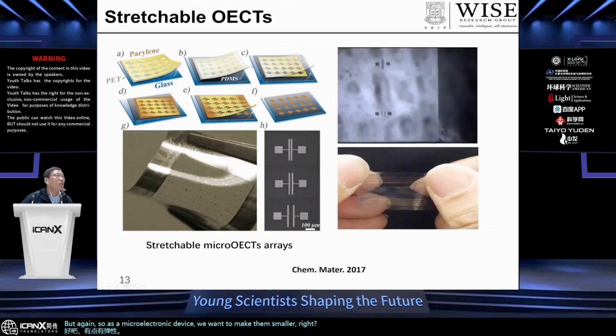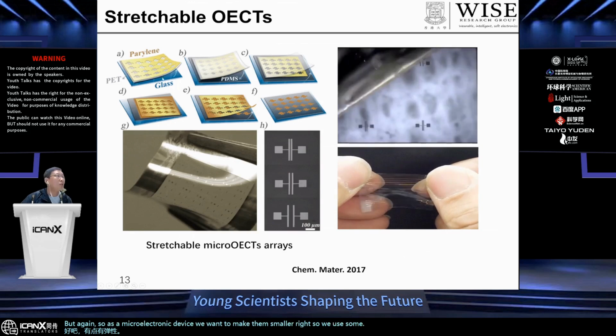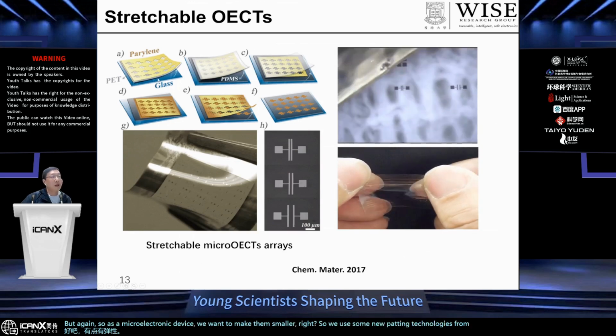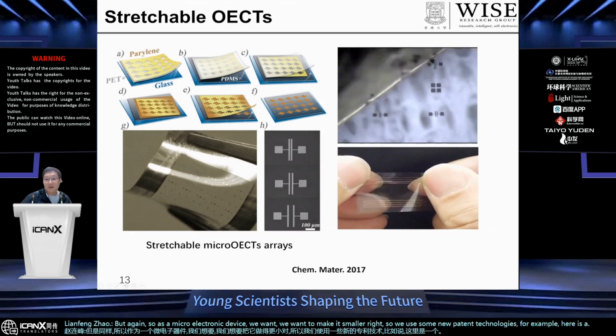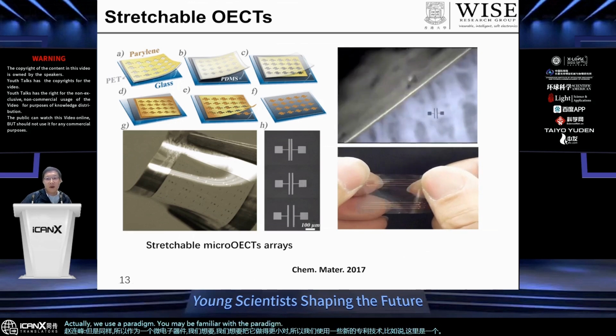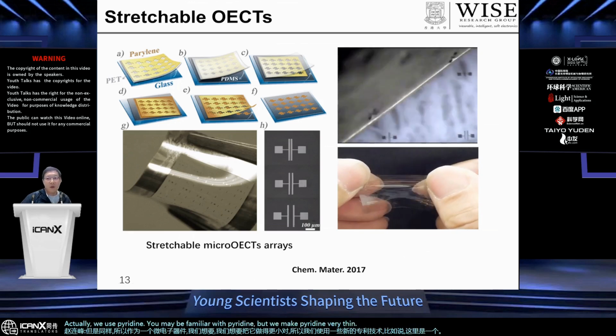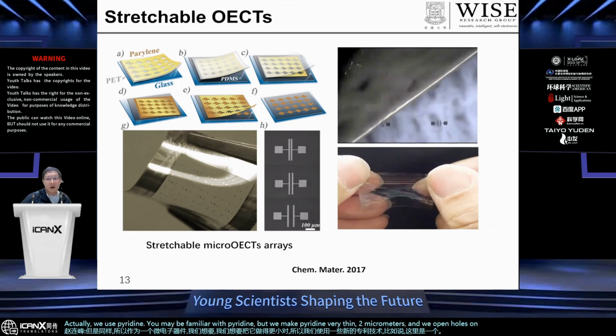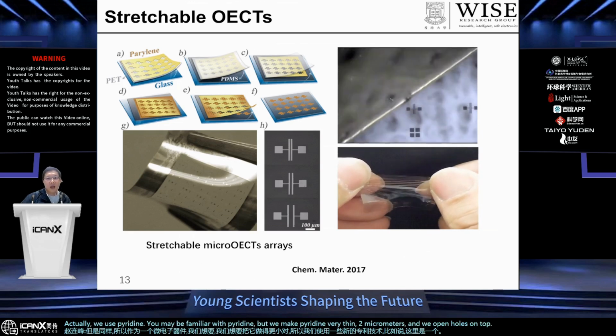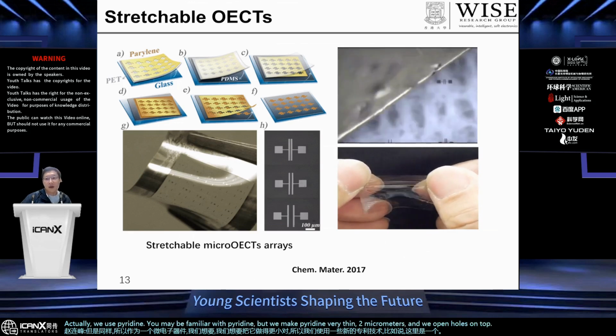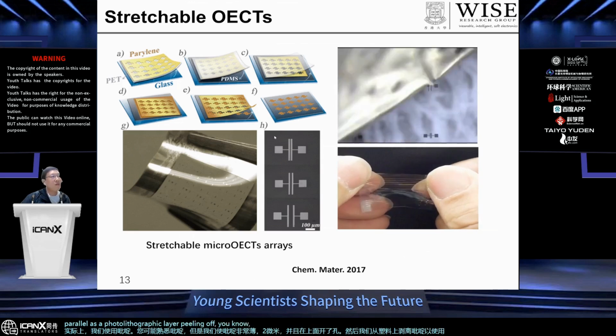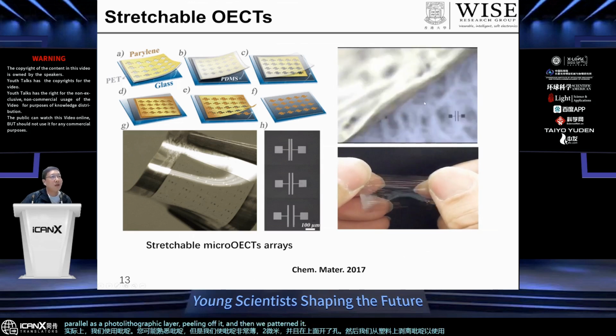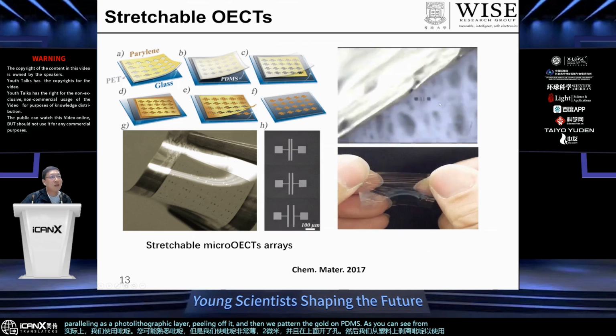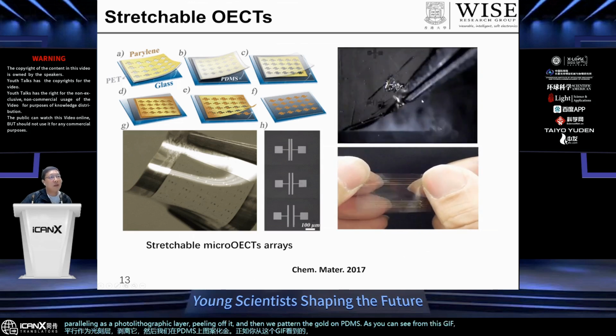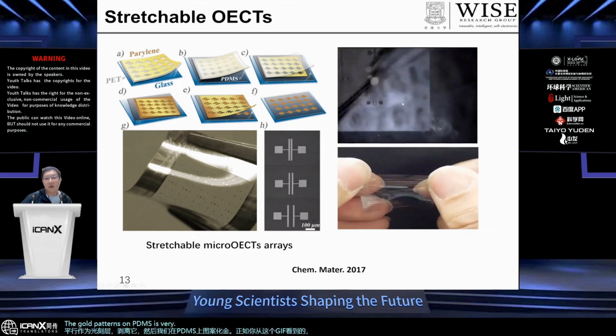So we use some new patterning technologies. For example, here we use parylene. You may be familiar with parylene, but we make parylene very thin, 2 micrometers, and we open holes on top. Then we peel off parylene from plastic, to use it as a photolithography layer. And then we pattern the gold on PDMS. As you can see from this GIF, the gold patterning on PDMS is very high yield.